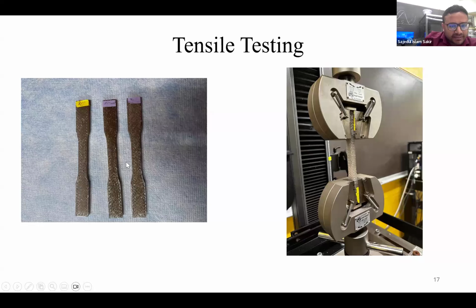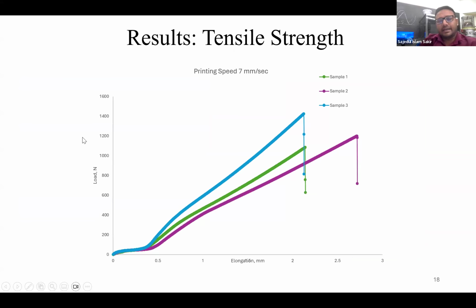So these are the samples I have printed from these settings, the modified sample. And I'm currently doing the tensile testing. It is still ongoing, so I can show some results of what I'm doing. This is the result when I'm doing the tensile strengths for printing speed 7 millimeters per second. I have printed 3 samples, and then I'm doing the load versus elongation curves. I'm doing the current analysis of it, so it's still ongoing. I haven't finished. I just show what I'm doing in our lab right now.